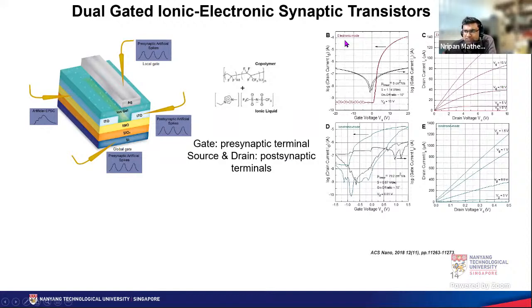This is the conventional testing when you use it with the bottom gate, given over here as electronic mode. And if you use it in the ionic mode, we sometimes call it ionotronic mode, or basically the top ion gel mode, you can see the characteristics here. One thing you can immediately see is that the operation gate voltages are very different for both the modes. In the electronic mode, we have to apply 10, 20 volts, while the ionic mode happens at much lower voltages.